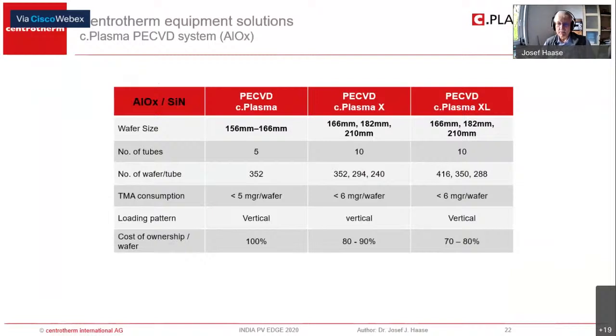It uses 10 tubes, and from the boat size for 166, it's still the 352, 294 for 182, and 240 for 210. We have also a very low consumption of TMA in the systems, which is less than 6 milligram per wafer. And when you look at the cost of ownership, if I set the basic system to 100%, you can save with the Plasma X about 10 to 20%.